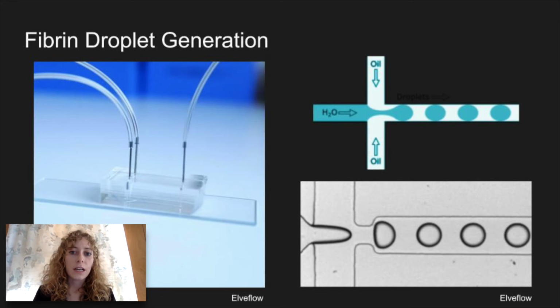And this is pictured by the image on the left, and the inlets are the two entrances into the device on the left of this image. After entering the device, the oil splits into two directions and meets up with the fibrin solution at an intersection, pictured by the images on the right. As both the oil and fibrin solution are pumped, droplets of aqueous fibrin are created. The formed droplets are guided to the outlet, which leads to another beaker containing droplets. These droplets will later be polymerized.